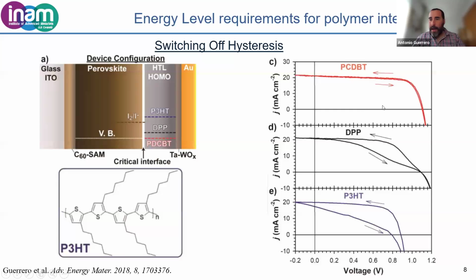Okay, now I will show you one of our articles in which we modify the material selective to holes. Here we use a series of polymers. We use P3HT, as you see here, as a hole selective material. The devices get a massive hysteresis in the IV response. As you can see here, the separation between the forward and the backward scan is very large.